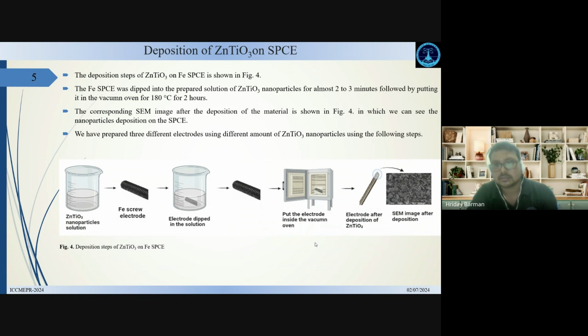After the deposition of this material on the electrode, we also took SEM images of the electrode, in which we can see the nanoparticles deposited on the SPCE. Using these deposition steps, we have prepared 3 different electrodes using different amounts of zinc titanate nanoparticles.